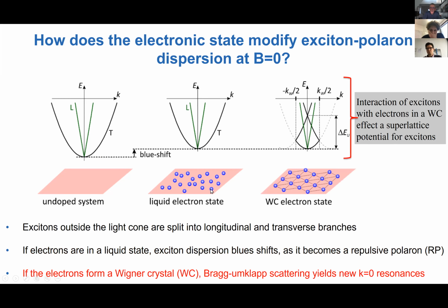Now, if these electrons form a crystalline state, a Wigner crystal state, then something else happens. The reason is that the excitons that interact with the electrons now see a periodic potential, and they backscatter off this periodic potential, which defines a new reduced Brillouin zone where the bands fold and lead to new resonances at zero momentum, or within the light cone. Therefore we have the possibility to see additional resonances because of the crystalline state, predominantly high momentum in character. These momenta could be two orders of magnitude larger than the optical momentum, and yet, because of Bragg scattering or umklapp scattering, we will be able to have new resonances at k equals 0.